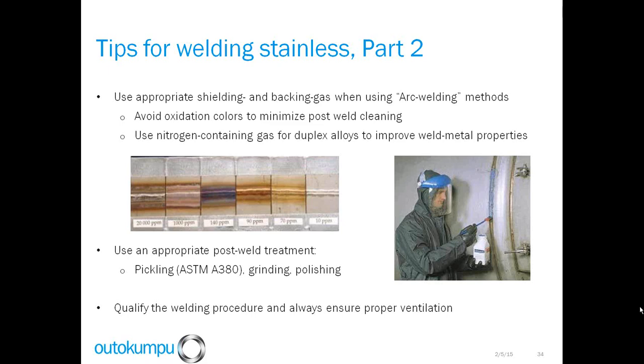The other thing is the appropriate shielding and backing gas. We should have minimal heat tint. Here you see in this slide what happens when you go to lower, 10 ppm oxygen on the right. We have very little heat tint. So these different colors represent oxygen contamination during welding. We want to achieve very low oxygen levels if possible, so we minimize the heat tint. If we do get heat tint, we're going to want to remove that either by chemical means such as pickling or by mechanical methods.